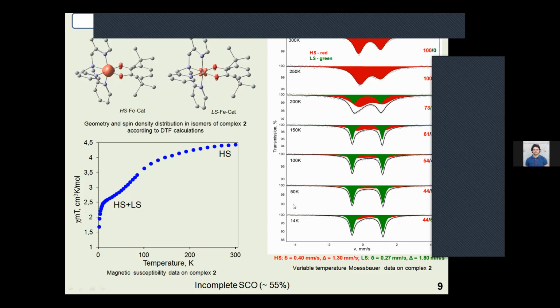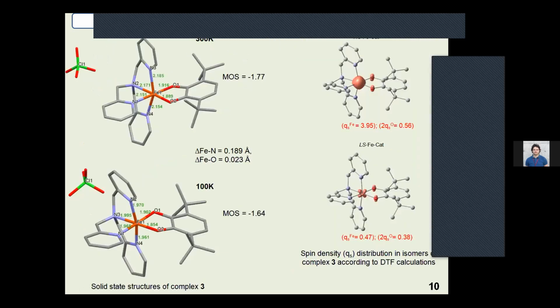Detailed analysis of Mössbauer data confirms this estimation, indicating the presence of 55% of low spin state in mixture with 45% of high spin state at given temperature. Analysis of the metrical parameters in compound 3 collected at 300 Kelvin clearly indicates the high spin state of the iron center.